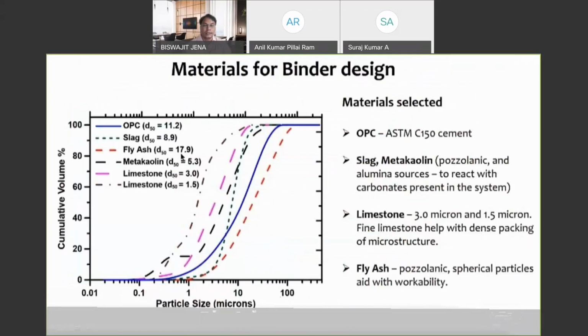So we have different types of materials, as I have already said, and you can see here that we have the cement, which has a median size of 11.2 microns, and for slag the median size taken here is 8.9, and for fly ash the median size is 17.9 microns, whereas for metakaolin the median size is 5.3.